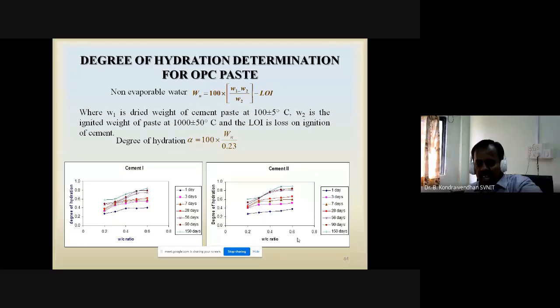The non-evaporable water content can be determined using the formula 100 times (W1 minus W2) divided by W2, minus LOI. Here W1 is the dried weight of the cement paste at 100 plus or minus 5 degrees, that is, after removing the evaporable water. W2 is the ignited weight of the paste at 1000 plus or minus 50 degrees Celsius for 3 hours, and LOI is the loss on ignition. Using the muffle furnace, you can determine this non-evaporable water content.